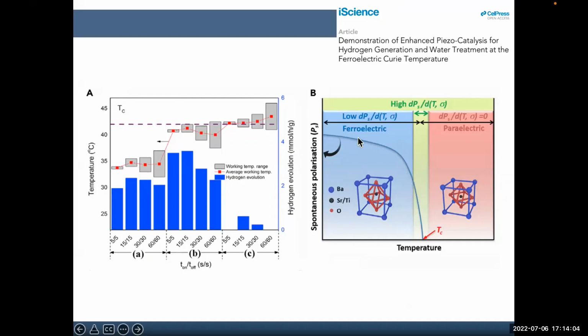So as we heat up our ferroelectric in the tetragonal phase, the polarization falls. As it begins to undergo a phase change to cubic, then there's no polarization. So that's the Curie temperature in a way.